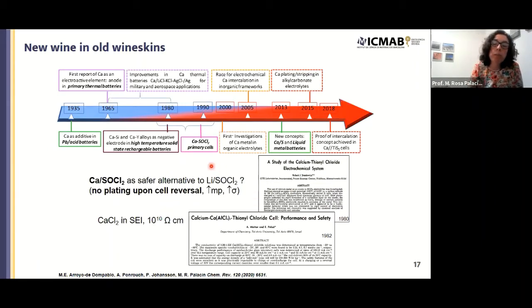And then because there was this commercial battery technology, lithium thionyl chloride, which is a primary technology again, it was suggested that using calcium instead of lithium would be an improvement for cell safety, because upon cell reversal, it would not be possible to plate lithium and have lithium dendrites, because plating of calcium was not possible. Another advantage is that calcium has a higher melting point and a higher conductivity. It did not make it to commercialization, and it stopped there. But the idea that plating of calcium was difficult remained, and this was deemed to be due to the fact that the passivation layers formed at the negative electrode and electrolyte interface do not enable transport of calcium ions.